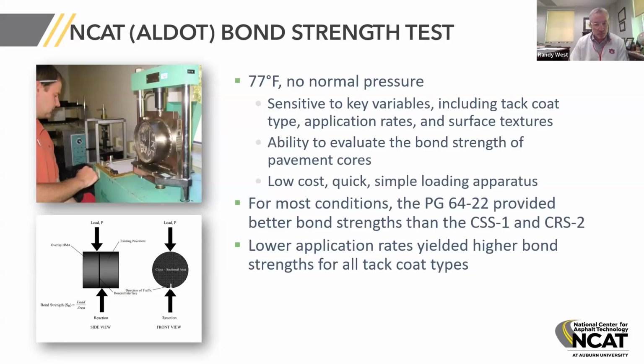And for most conditions, as I mentioned before, the PG 64-22 straight binder provided a better bond strength than the two emulsions that we tested. We also observed that the lower application rates in the laboratory test provided the higher bond strengths for all the tack coat types. So sometimes you think, a little bit is good, a little bit more may be better, but that's not always the case with tack coats.